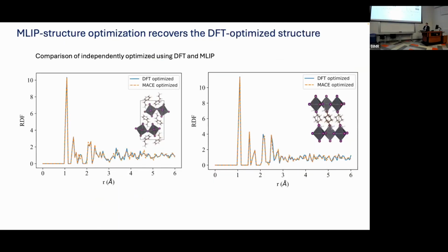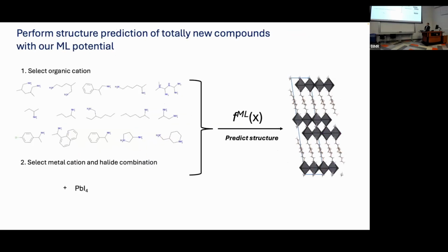We can also validate how it looks for the structures itself relative to DFT. Since it's been trained on DFT, it should look very accurate. Here, these are RDFs, the radial distribution function. This is basically a continuous sort of catalog of the bond distances in the structure. And the fact that the blue line and the orange line overlap implies that they're very accurate, that the model that's been optimized reproduces the DFT optimized structure, which is an independent calculation.